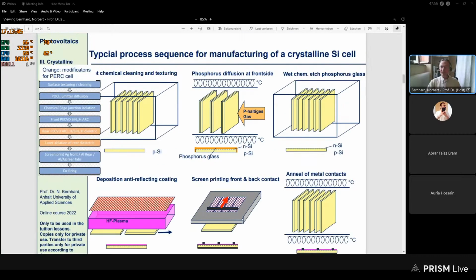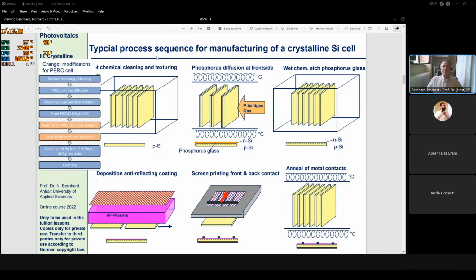Okay, here we have an overview of the typical process sequence for manufacturing of a crystalline silicon cell. It starts with wet chemical cleaning and texturing. Here we have the wafers. It's just p-doped material. They come into a bath of some etchant. It could be either an alkaline or an acidic bath. For monocrystalline material, one would use an alkaline bath. For multicrystalline material, one would use an acidic bath.